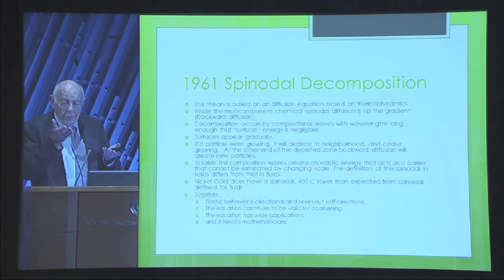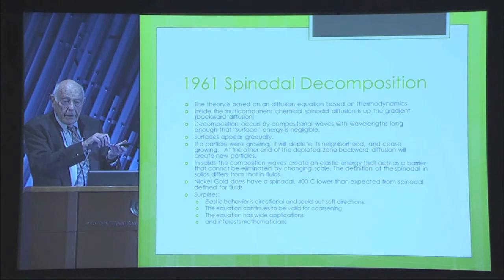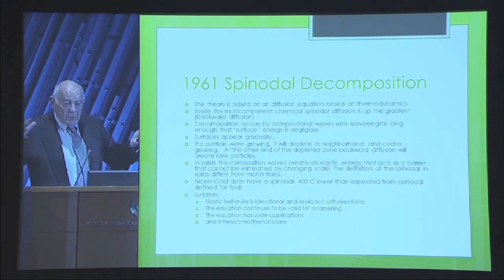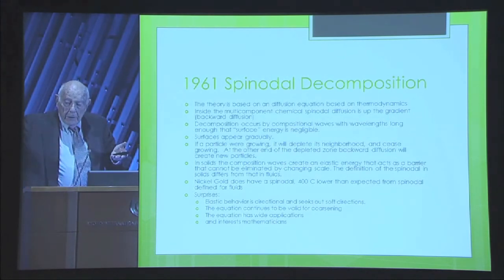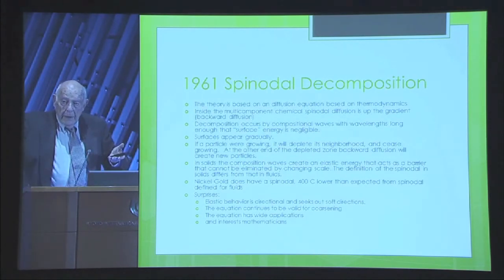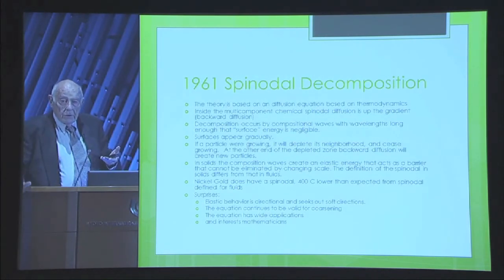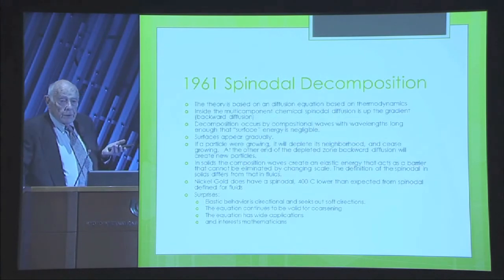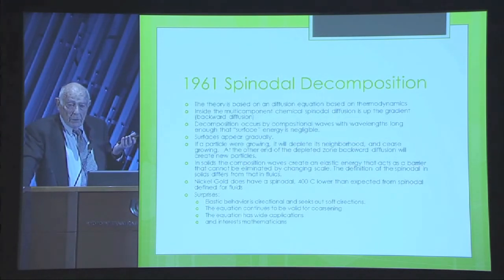Whereas in ordinary diffusion, material moves from where there's high concentration to low concentration. In this particular case, the thermodynamics dictates that material will move from low concentration up the gradient and concentrate on the high thing. So the cloud sort of collapses. But if the cloud collapses here, over here there is another place where it's now collapsed, but here it hasn't, so it starts building up in this direction. And so the solution is sinusoidal, and it is the solution to a diffusion equation, but it is a different diffusion equation.